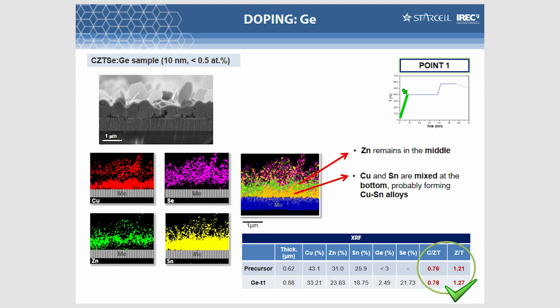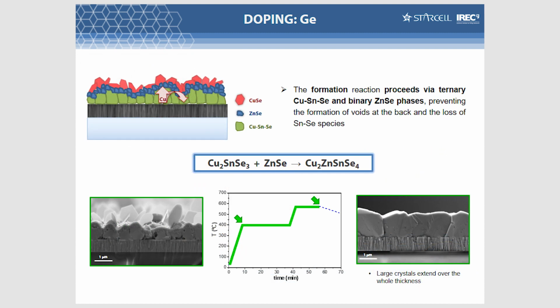Nevertheless, when we include germanium, we observe a very different picture. We have a very good copper and tin mix, and also we don't observe tin loss during our reaction. This means that in some way germanium prevents the tin loss. And analyzing all this process with Raman spectroscopy and X-ray diffraction, we observe that the reaction mechanism changed drastically. We are only forming a copper, tin, selenium ternary compound that reacts with zinc selenide forming kesterite.